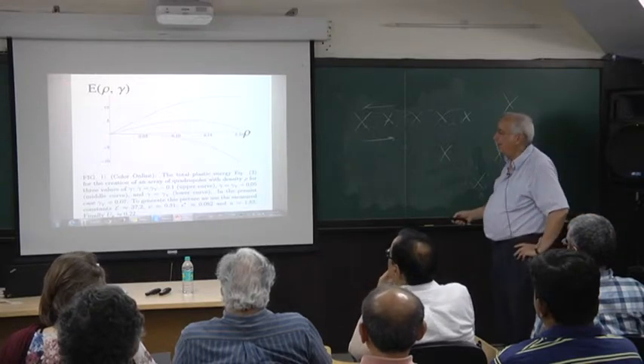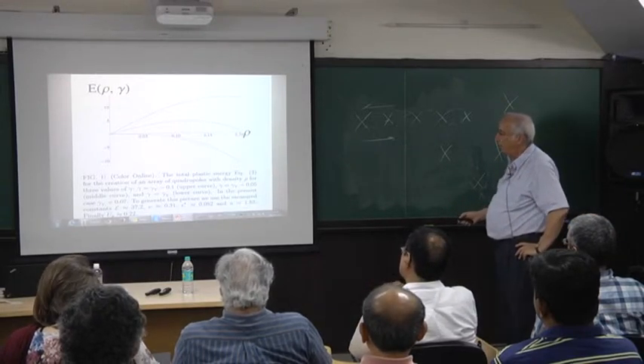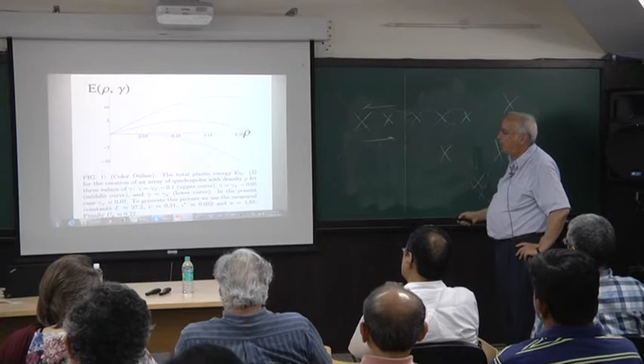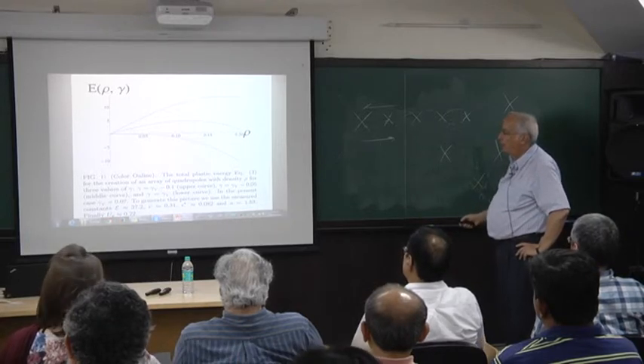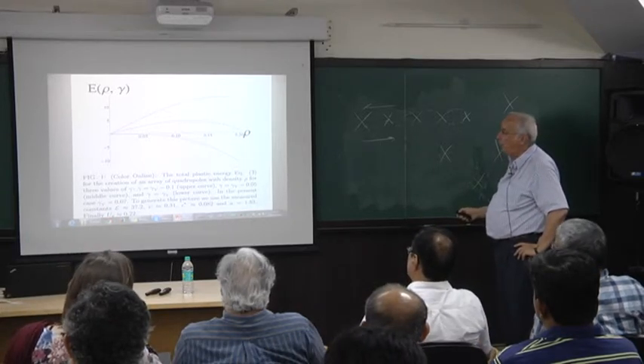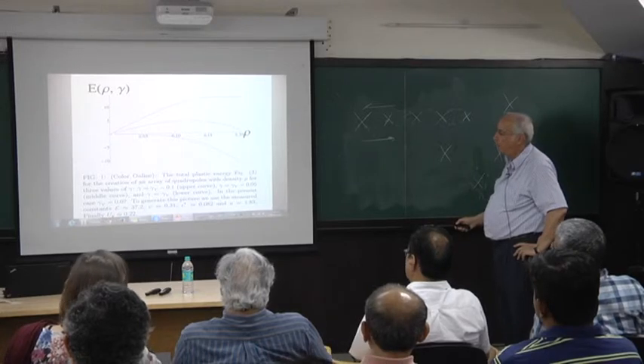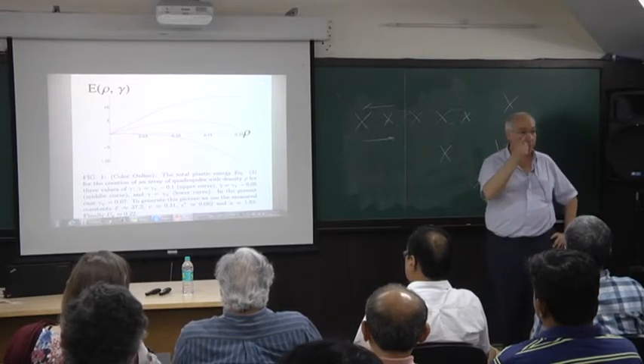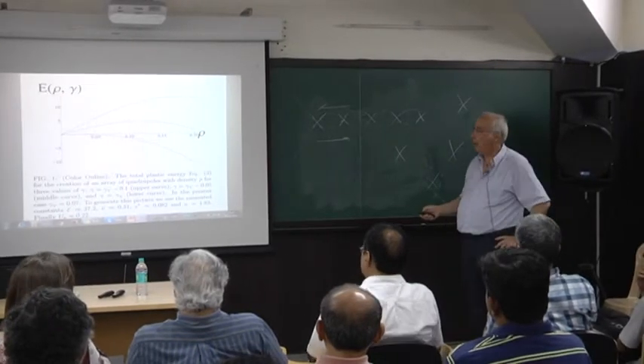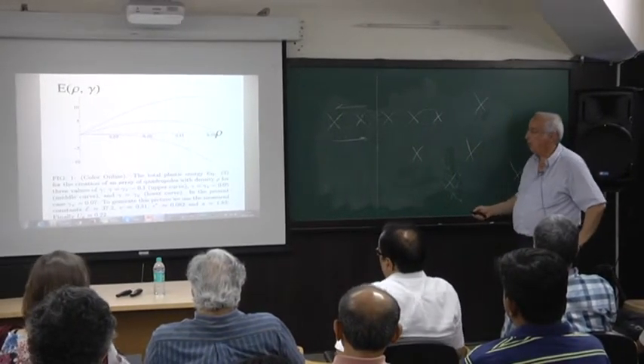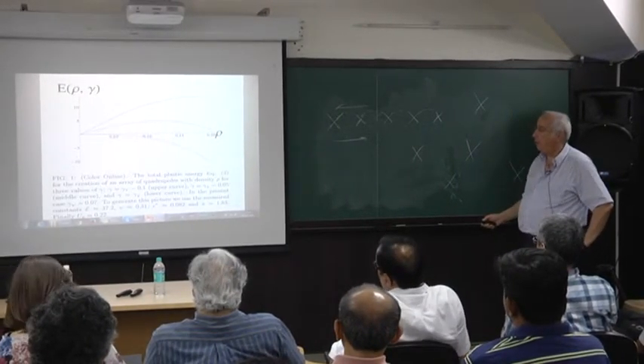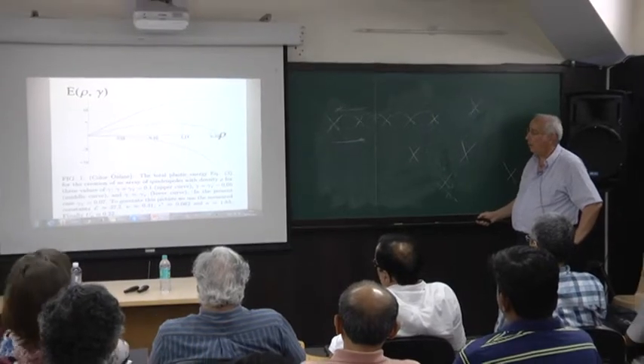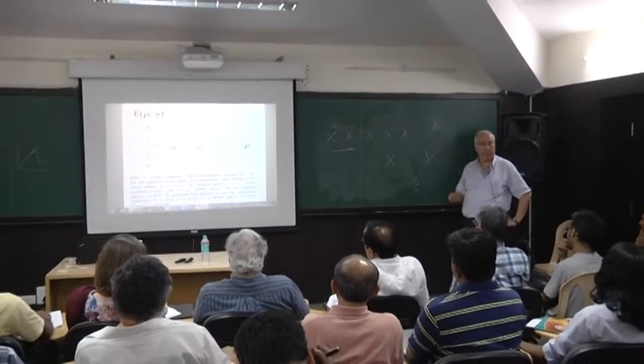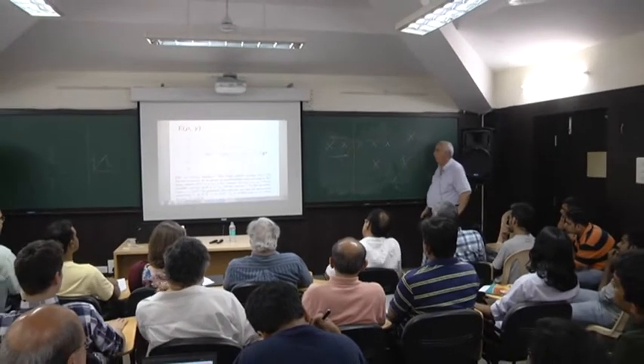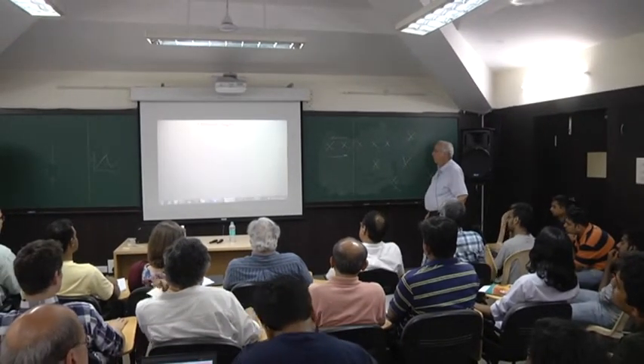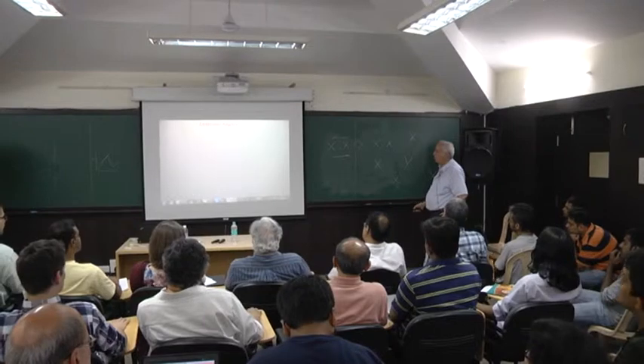As a function of the density of the Eshelbys for different gammas. So for small gamma, it looks like this. Okay, for small gamma, it looks like this. Now you want to minimize it, there's only one minimum at rho equals zero. This is a single one. Okay, that's the thing. Now you increase gamma, and this becomes flatter and flatter. At some point, you have a crossover, and this occurs, of course, when gamma equals gamma yield. So, okay, so this explains